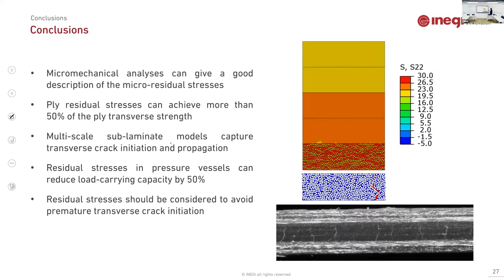Okay, so to conclude, micromechanical analysis can give a good description of the micro-residual stresses and what happens at this microscale level, which is very complex to do in an experimental way. Considering the ply residual stresses that are developed during manufacturing is very relevant because, depending on the laminate configuration and the geometry, we can reach a higher amount of stress that can trigger, for example, the transverse failure mode that could be critical in some applications. Okay?